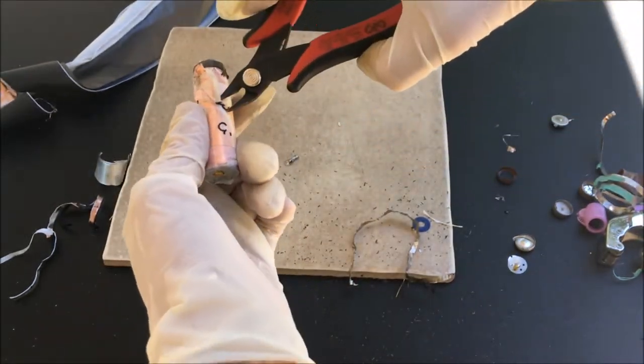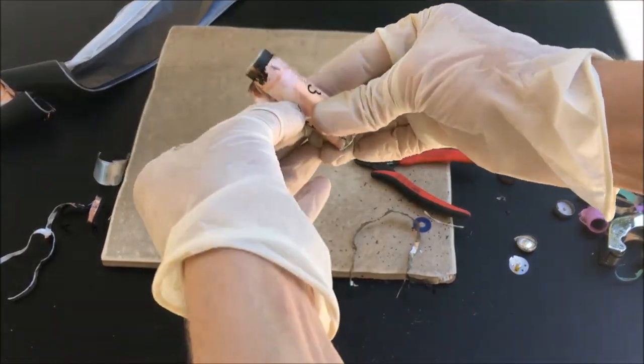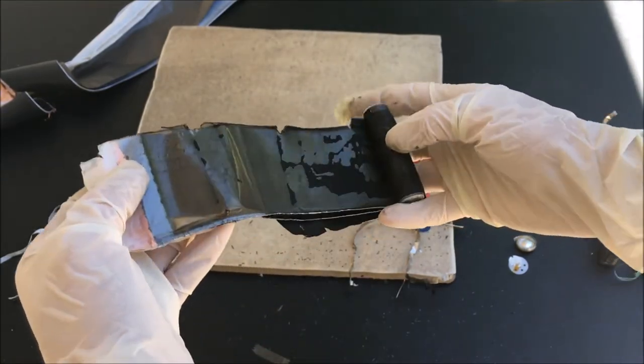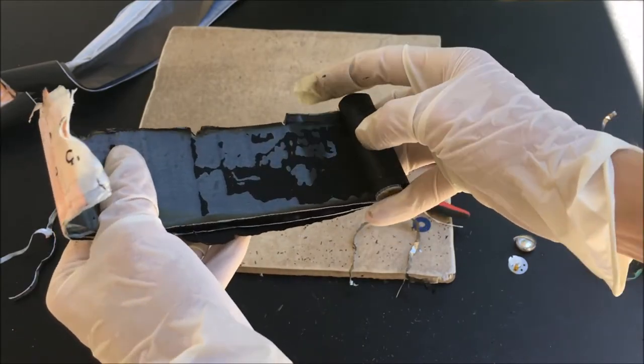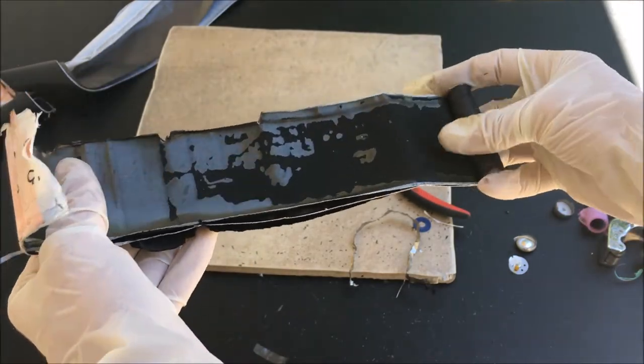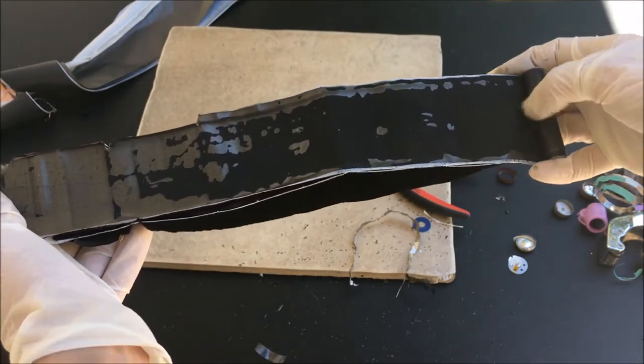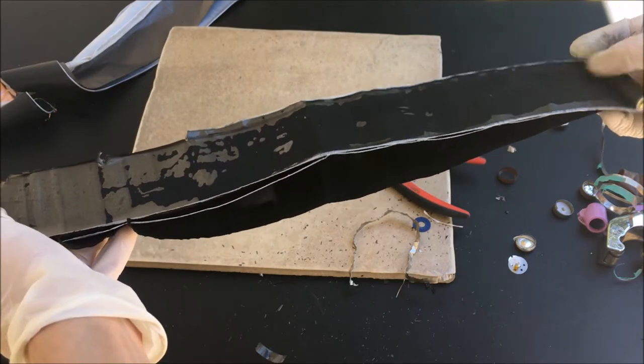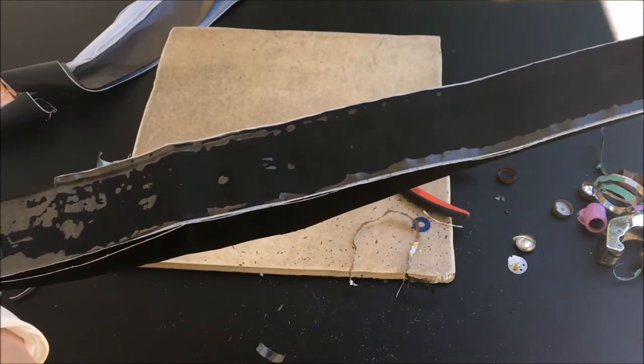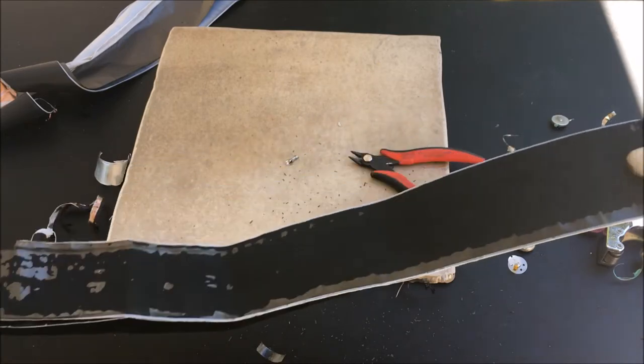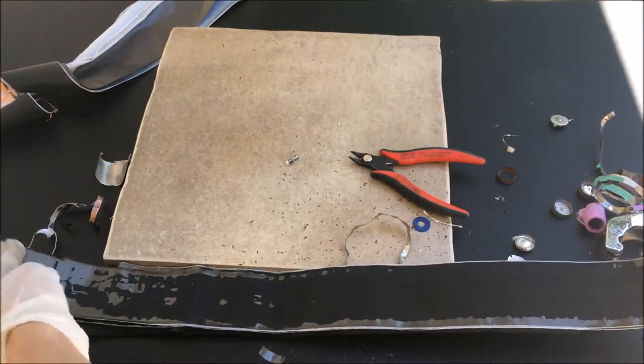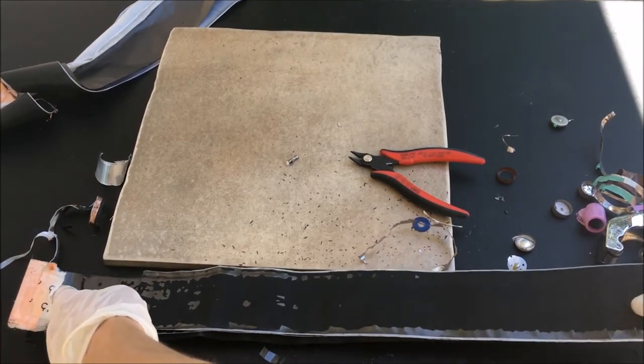The consistency is obviously not as good in here. As you can see, it's very sort of hit and miss, haphazard application, and I suspect this may have a lot to do with the reduced performance of the cell. Additionally, the length of cell is much less—actually, well actually no, no it's fine, it's about the same. But you can see the real limitation here looks to be that the application of actual electrode material—I'll let you see all the way to the end—is much less consistent. And there it is—that's all the, all that black stuff, all that sort of powdery looking stuff is our material. I'll see if I can hold it side by side against the LG. The LG—also feel the plastic feels a lot thinner and lighter, which could help a lot with the internal resistance. So let me set these out side by side and we'll compare them.